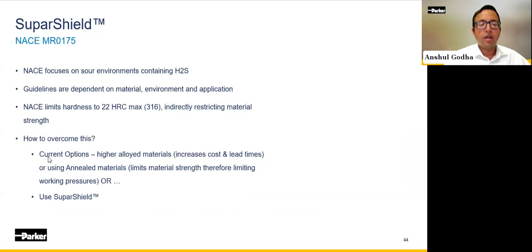Another interesting fact is the effect of SuparShield towards sour service type of environments. NACE, now called AMPP, developed a now famous standard, NACE MR0175, back in 1975 to deal with all the major issues that were happening in the field in sour service. The guidelines that NACE came up with are dependent on the material, the environment, as well as the applications. One of the key ways that NACE tackles the effect of material on stress cracking is by limiting the hardness of the alloys. So for 316, that usually translated to about 22 HRC max. While that worked in terms of prolonging the life towards stress cracking, it also indirectly put a severe restriction on the strength of the material that can be used in such an application.